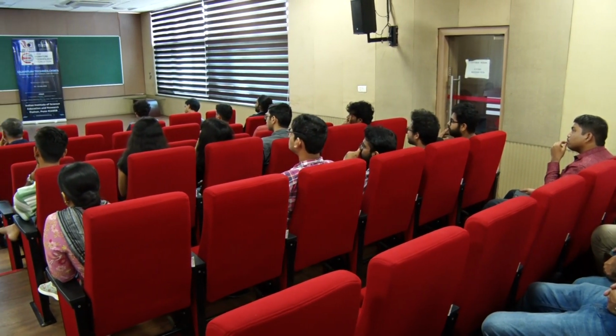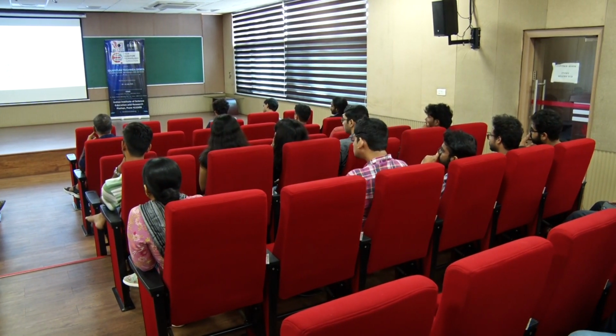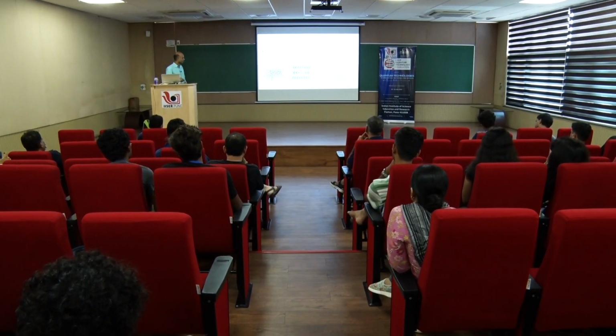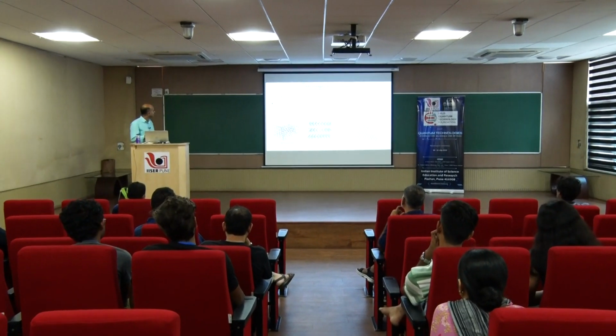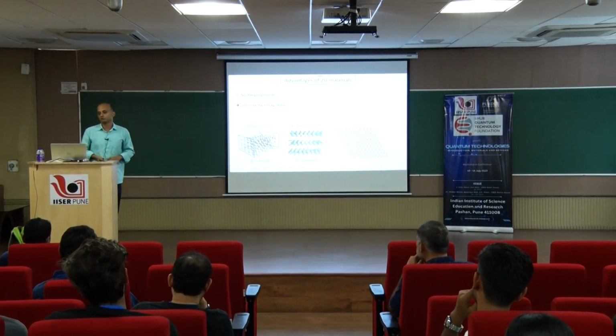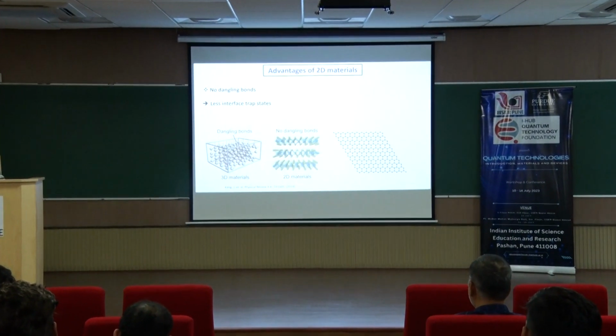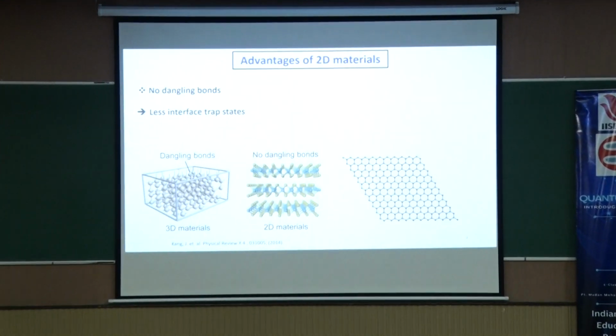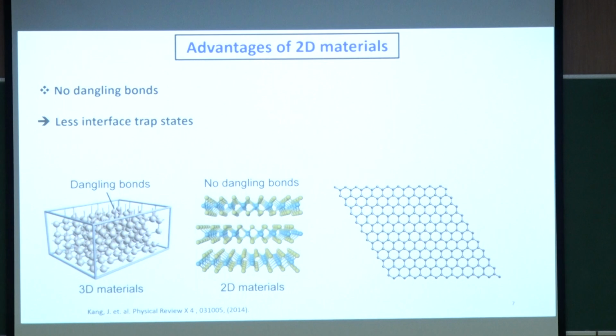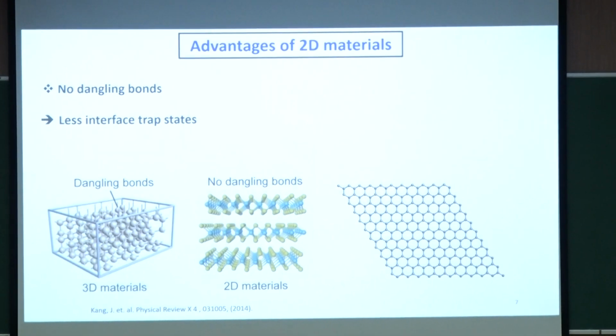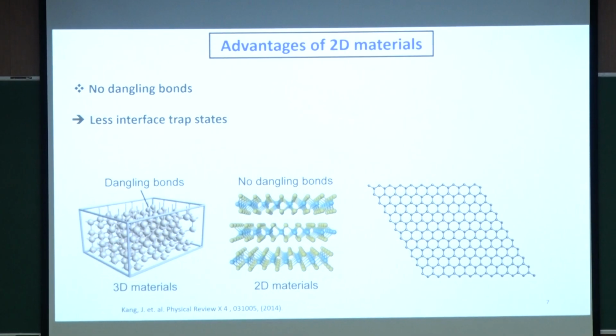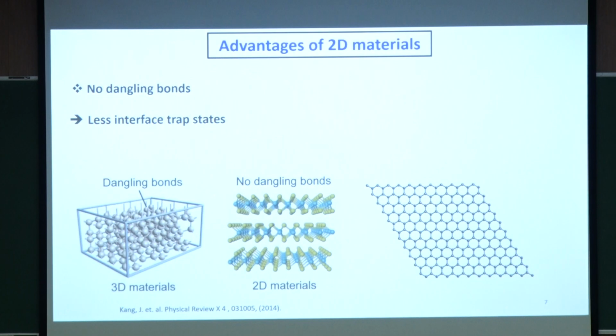Another advantage, and this is a great advantage, is that there is no dangling bond. Being van der Waals materials, not only graphene, all these MoS2 or layered materials don't have any dangling bonds, and that helps in various ways. One simple but most important thing is that they have very few interfacial traps. If you take silicon and try to thin it down to make a silicon transistor, then below a certain level the contribution of the surface dangling bond traps will be more than what you are expecting from your channel. So it is very difficult, you need to passivate and do a lot of tricky stuff.